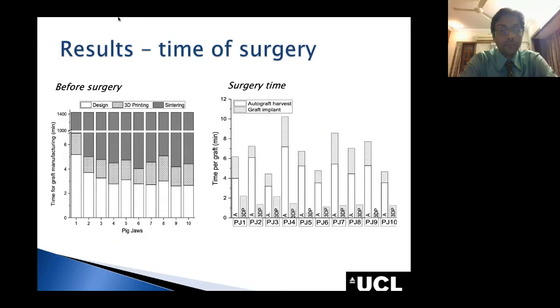The design, once all these factors were already optimized, took on average less than 5 minutes, also because the user was experienced in that and the process was already optimized. The 3D printing step was 2 minutes, and the sintering time took around 25 hours. But the good thing is that all these pig jaws could be sintered at the same time. So in total, I would say that the overall pre-surgical design, 3D printing and sintering took around 1.5 days.